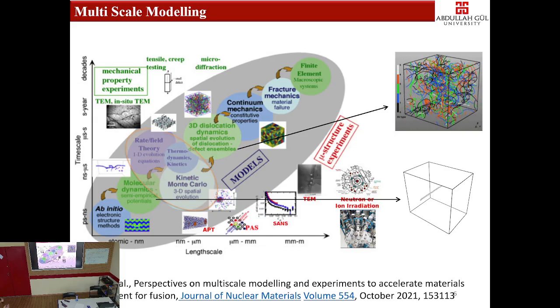So FCC always deforms with edge dislocation, and once we start moving the edge dislocation, we have Shockley partials and stacking fault energy. So let's keep one thing in mind. Can you tell me any FCC material that you know? Like copper, like gold, like aluminum. These are very soft materials, right? If you think about 100% aluminum, like a paper clip, you can easily bend it, or gold, you can easily bend it. The reason is edge dislocation.